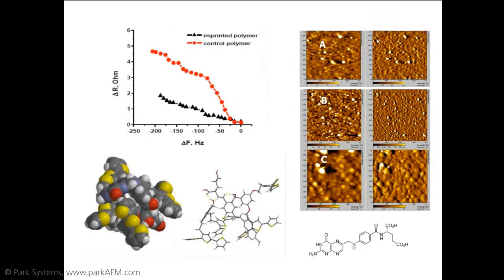Now let me focus then on the value of atomic force microscopy. Atomic force microscopy is one of the characterization methods that we use. In fact, it's quite interesting and invaluable in that it gives us a morphology differentiation between films that are printed, imprinted, sensed, and washed. And that means that we can monitor the changes in this morphology, not necessarily observing any changes in porosity, but each type of film has a particular morphology that is quite important in terms of improving its efficiency. In fact, in some cases, we've seen an increase in porosity by certain treatment procedures that we can visualize directly by atomic force microscopy or AFM.